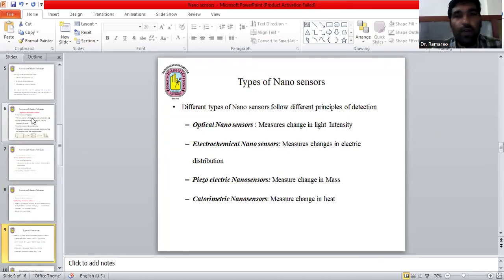When a molecule of ammonia is present along with water vapor, it makes the carbon nanotube more conductive by donating 1 electron. On the other hand, in the presence of 1 molecule of NO2, the nanotube becomes less conductive by the release of 1 electron from the carbon nanotube.